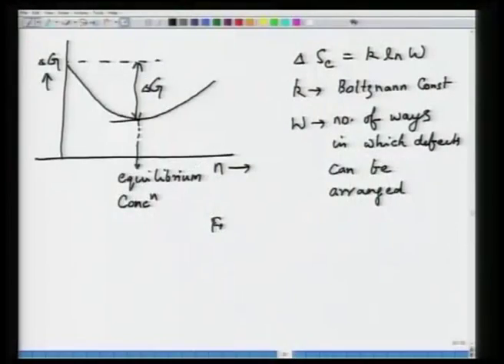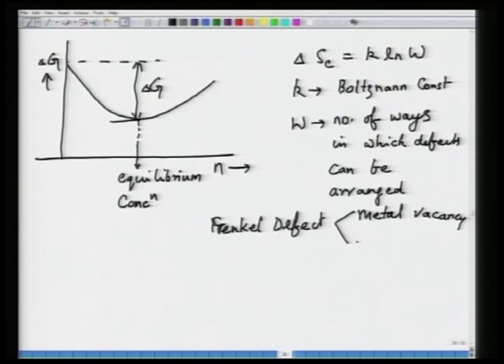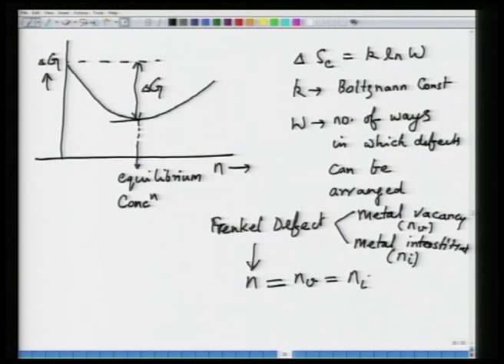So let us say now when you form these Frenkel defects, a Frenkel defect would mean you have a metal vacancy and you have a metal interstitial. Now let us say total number of defects is equal to n. This is going to be equal to the number of vacancies nv, and this is going to be equal to the number of interstitials, which is ni. So, just by looking at the defect reaction itself, this is very simple. The number of Frenkel defect pairs n is equal to the number of metal vacancies and the number of metal interstitials.